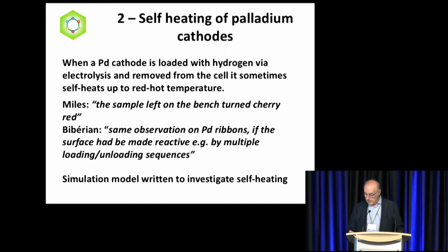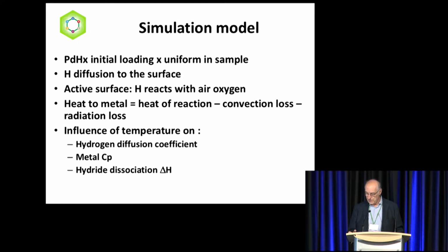So, what could I do? I have no palladium to play with, so I just wrote a simulation model to investigate this, a numerical model. You give some assumptions and you get some results. So this model takes into account the hydrogen diffusion to the surface. The surface is active, so every atom of hydrogen coming to the surface is immediately oxidized, and so the hydrogen concentration at the surface is 0, as a hypothesis.